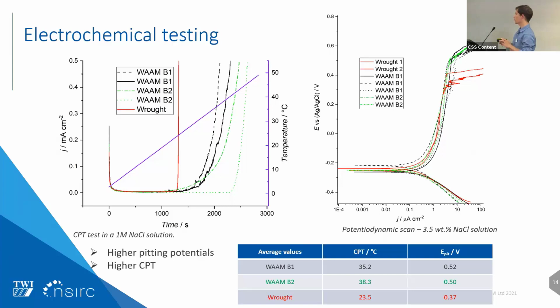Here on the table, you can see all the different temperatures that we had for WAAM B1, B2, and for the wrought. We have a 3-degree difference between WAAM B1 and B2, which is not significant considering that the CPT test technique usually gives widespread results, or can. So a 3-degree difference, especially on a sample of this size, is not enough to say that you have a clear difference between the two.